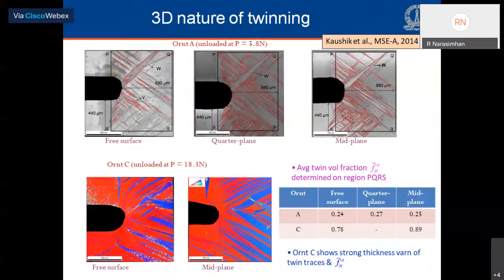On the other hand, if you look at orientation C, which is shown at the bottom, the IPF maps on the free surface and the mid plane, you see a more pronounced thickness dependence, with the mid plane showing more profuse twinning as compared to the free surface. So the average twin area fraction is about 89% in this case from the unloaded specimen for the mid plane, whereas it's around 78% for the free surface. There's a bit more dependence on the thickness in this particular case.